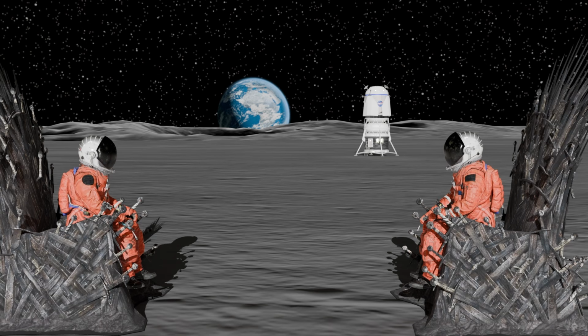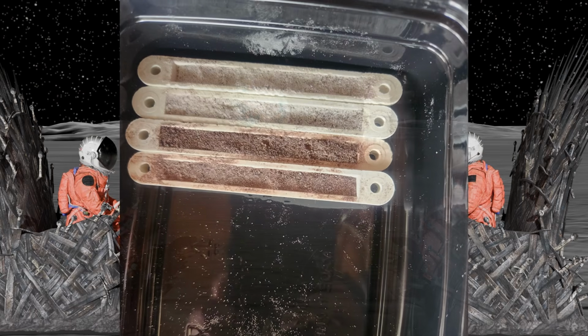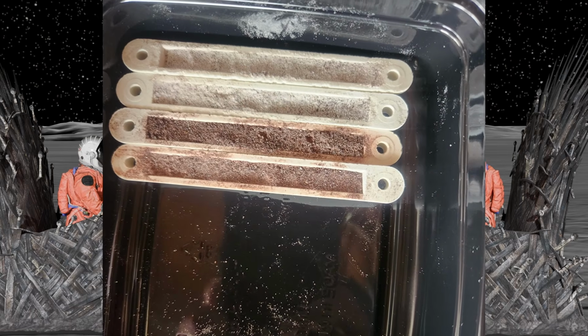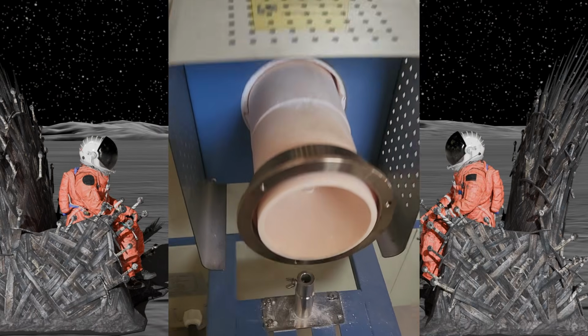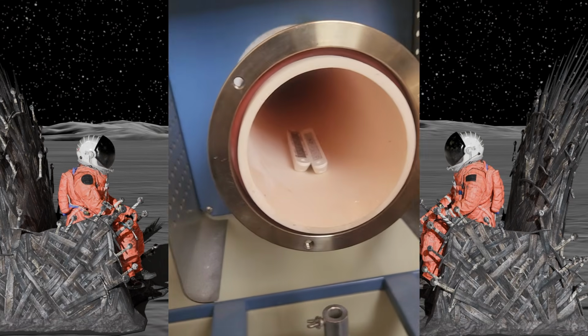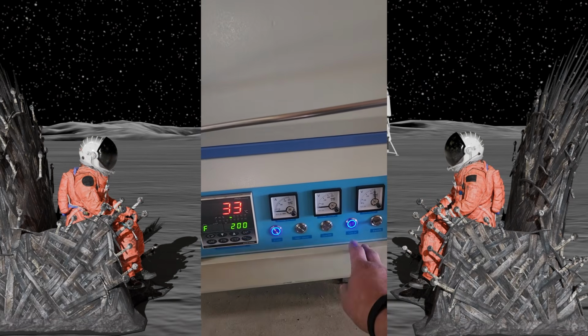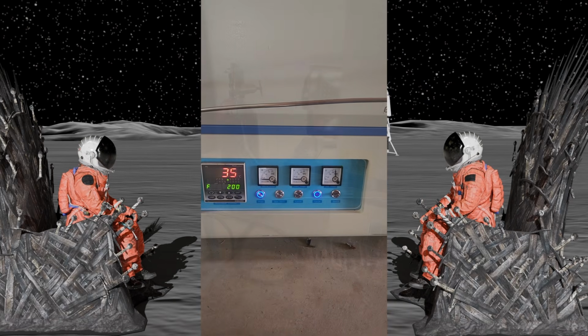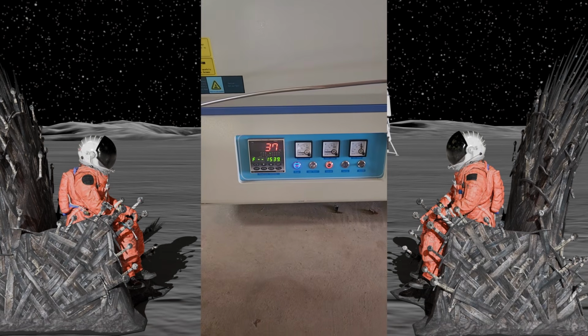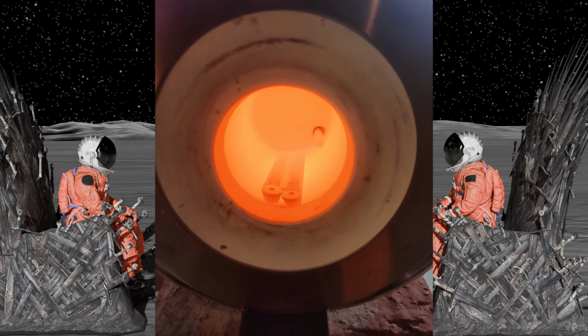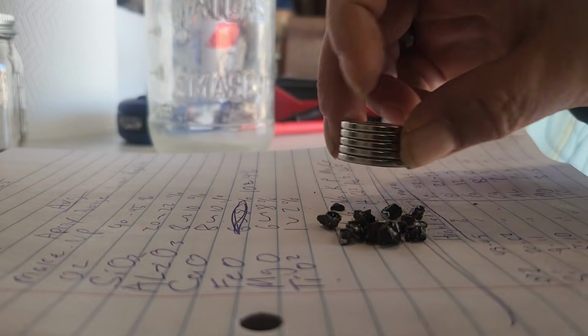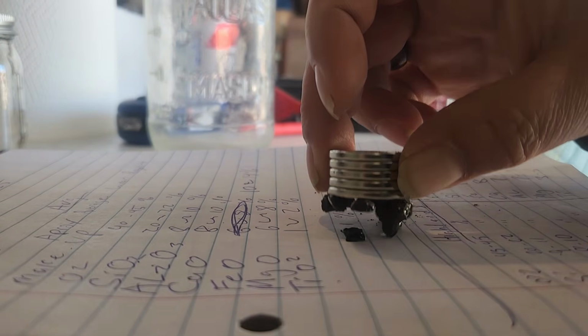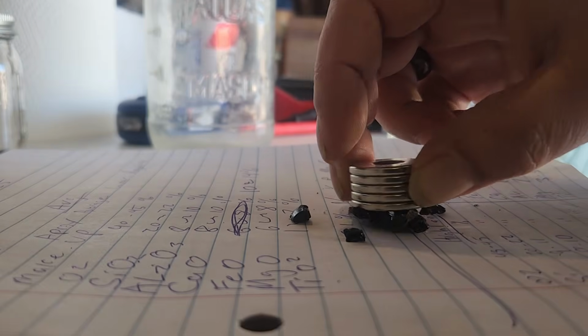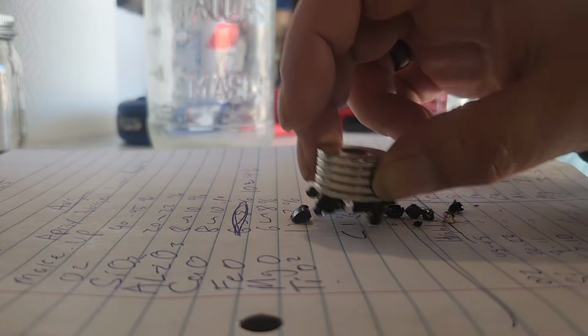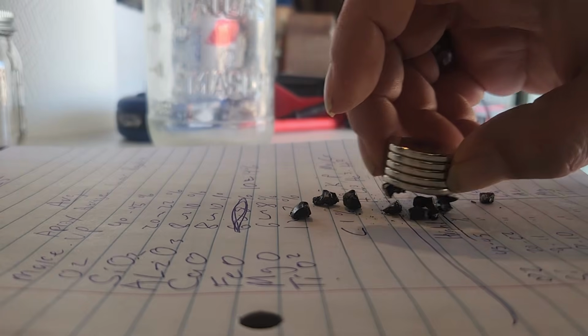Yes. When you're thinking about a process and you probably want to grab everything that you can out of the lunar regolith, one of the first processes that you probably want to go across is your iron. There is a limited amount of free iron, and that free iron is also bonded to a lot of FeO, iron monoxide. So one of the processes that we explored was a vacuum hydrogen reduction. We found that it actually reduces iron extremely well. And one of the main reasons we went with this is because you're not only producing iron, but you're producing oxygen from the lunar regolith, which is a valuable product that can be sold.